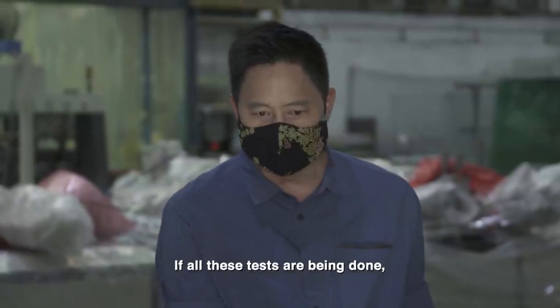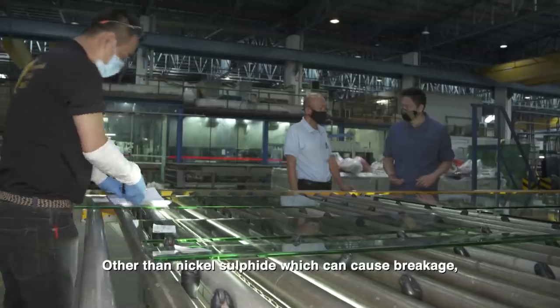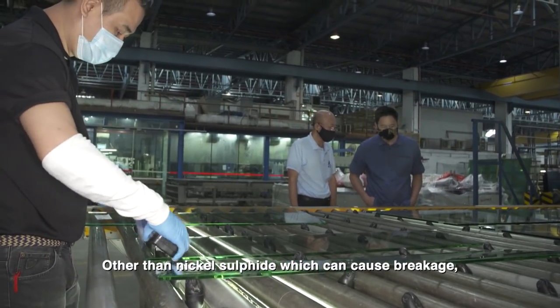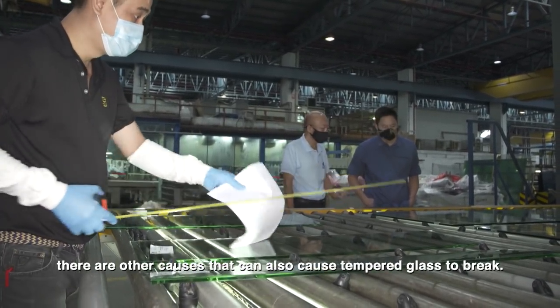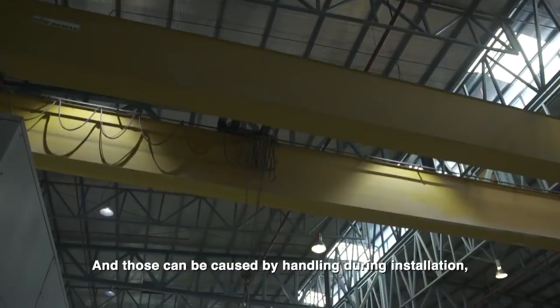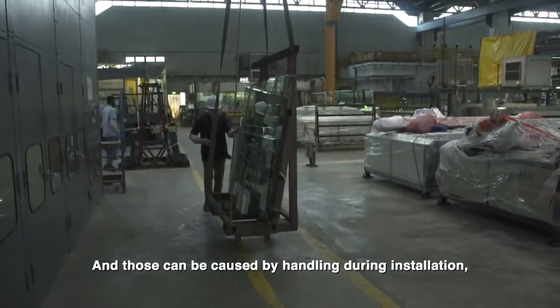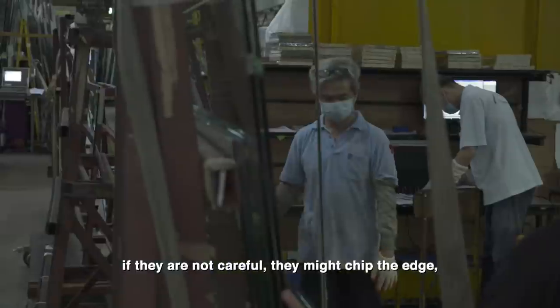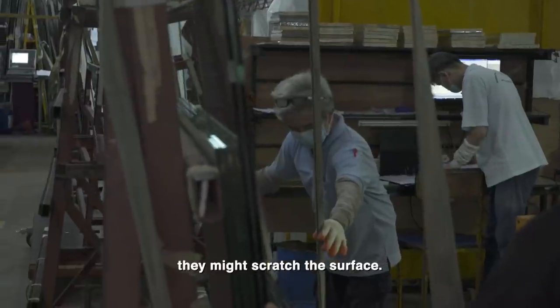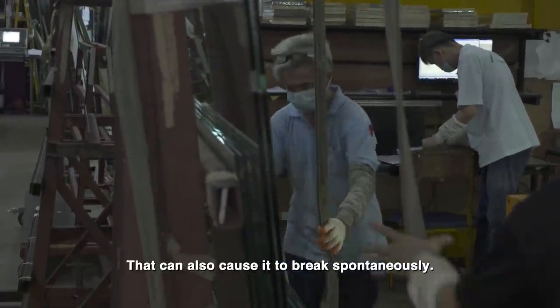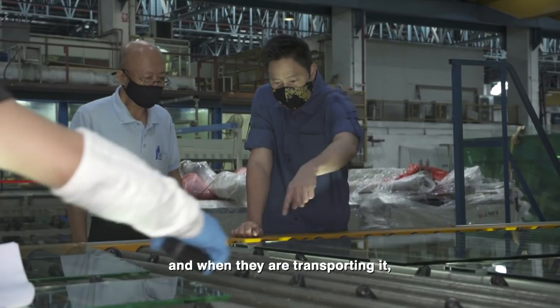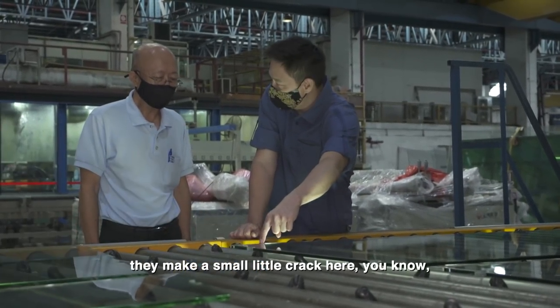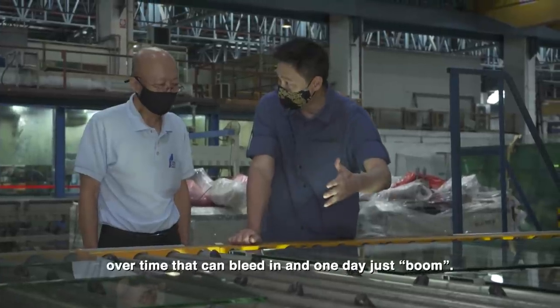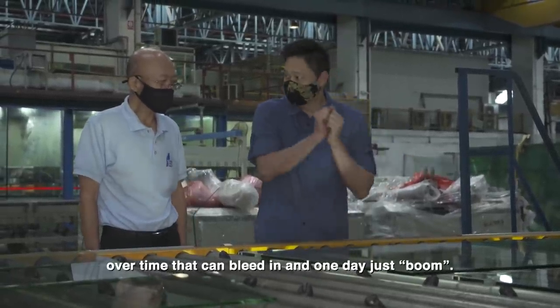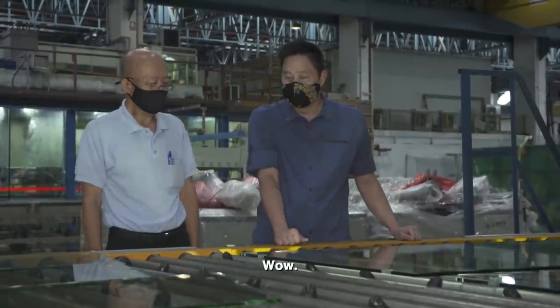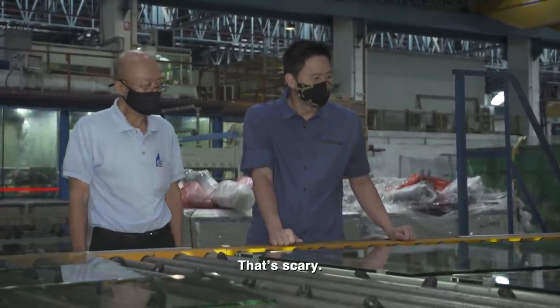So if all these tests are being done, then why is the glass still breaking? Other than nickel sulfide caused breakage, there are other causes that can also cause a tempered glass to break. And those can be caused by handling during installation. If they are not careful, they might chip the edge, they might scratch the surface. That can also cause it to break spontaneously. So in other words, if this is my shower door and when they're transporting it, they make a small little crack here, over time that can bleed in and one day just boom. Yes, that's right. Wow. That's scary.